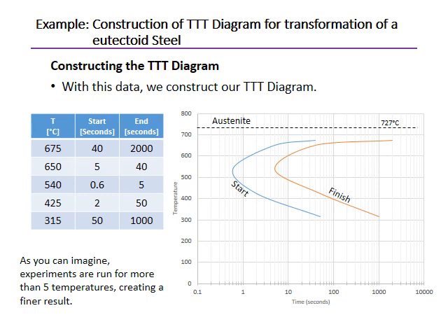So below that, austenite is being transformed. In this case, we know that below 727 Celsius, austenite is being transformed into pearlite, which is the eutectoid phase. So we know that this is pearlite. Know that pearlite is a mixture of ferrite plus cementite.